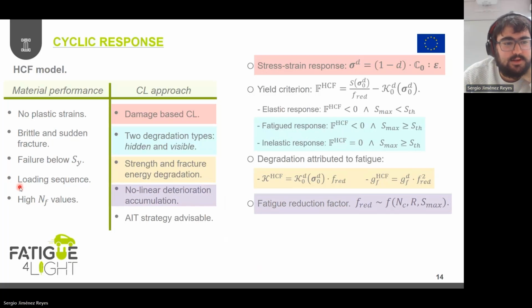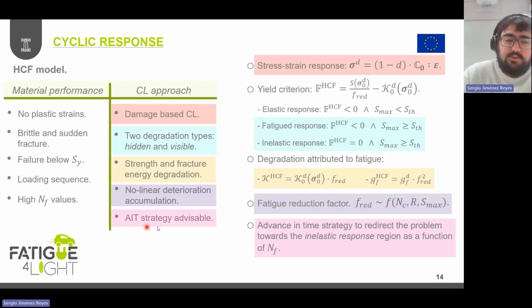Another feature to be captured for this high cycle fatigue response in materials is the loading sequence effects, which is really related with the fact that the nonlinear process taking place along this fatigue phase of the material should be nonlinear. And in order to achieve that, what we've done is describing this fatigue reduction factor as a function of the number of cycles being applied in the element, the reversion factor, which relates the minimum and maximum stresses appearing in the material, and the maximum stress level. And then finally, considering that usually this high cycle fatigue phenomenon develops, or the failure takes place, for really high numbers of cycles, it is really advisable to integrate an advancing time strategy together with the constitutive model. And we also do that in the constitutive law that we're proposing.